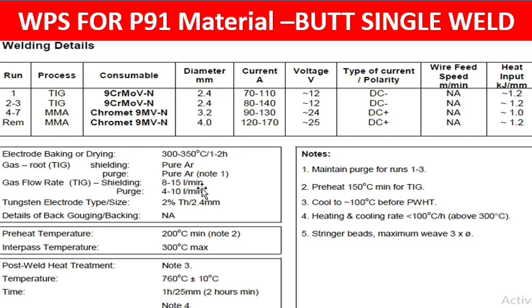Tungsten electrode type is 2% thorium, and the size is 2.4 mm. Details of back gouging: not applicable. Preheat temperature is 200 degrees centigrade minimum, but 150 degrees centigrade is the minimum for TIG. We can use 150 degrees centigrade minimum. Interpass temperature is 300 degrees centigrade maximum.